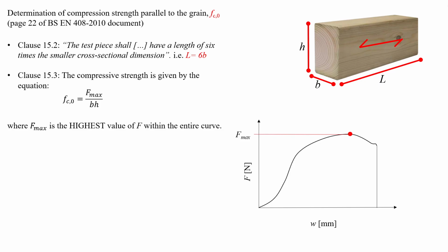If it's a hardwood like this one here, it didn't behave quite like that. This part here was elongated, it was still going down. It never got to a cliff face because we stopped the test before we eventually broke it. But it had already failed, the Fmax was already reached. It's never going to get any stronger, but the test never fell off a cliff. The softwood will fall off a cliff. It will just break fairly quickly after the Fmax is reached.